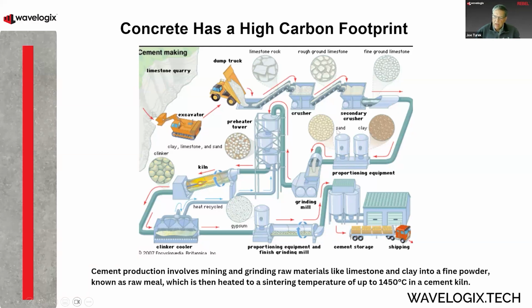And then we mix in things like clay and sand to be able to create a chemical reaction. We grind it again, mix that all up. We start to heat it, and then we fire it in a kiln at 1450 degrees centigrade. We take that stone and drive all the moisture and water out of it and create a new stone, a combination of that sand, clay, and limestone, into a clinker. So we create another stone, and then that clinker is cooled.